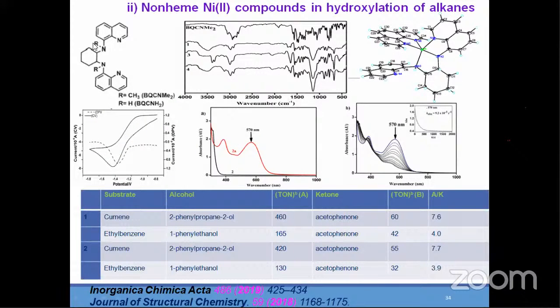Then we again did nickel chemistry with other ligands, cyclohexane-based ligands. Interestingly, you can see we replaced this R group with a methyl group as well as H groups, and we did the catalytic reaction. We characterized these compounds by structure and CV, and some intermediates were obtained. However, we could not give clear-cut evidence for that. Of course, we did some catalytic reactions with alkanes. We got this data published in Inorganica Chimica Acta in 2019, and also in the Journal of Structural Chemistry.